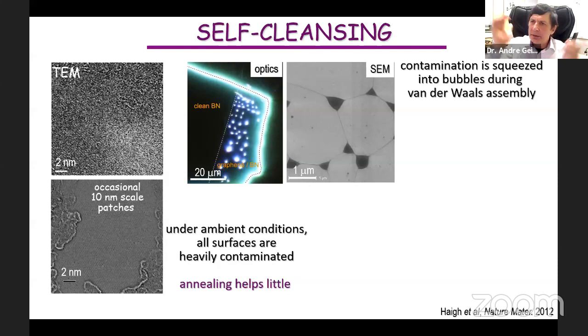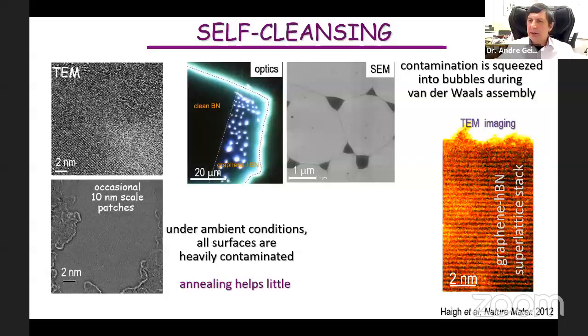So when you put two crystals on top of each other, this contamination doesn't like to live there. It segregates into the pockets, which you see here. You put one crystal on top of the other, and all contamination goes into those pockets and leaves a clean space. And you can make a cross section and find out that there is no contamination left. In this case, it's a cross-sectional picture of a graphene boron nitride superlattice. There are about 10 bilayers of graphene and 10 bilayers of hBN here, and you don't see any contamination between. There is essentially perfect assembly.